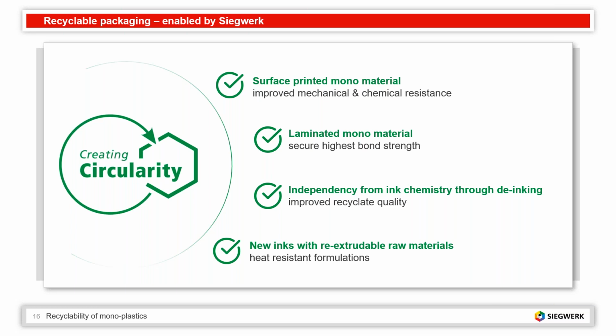Okay, great. Then we have another question about OPVs. Does heat-resistant OPV lacquer prevent shrink effects of PE or PP under heat, or does it prevent sticking to the sealing jaws? The latter. I mean, you can't keep polyolefin from melting. They have their melting point, and when you go past that, they will melt and also shrink afterwards. But it prevents the sticking, and to some extent it also gives some stability because it's a 2K layer, so it also gives a little more mechanical stability.